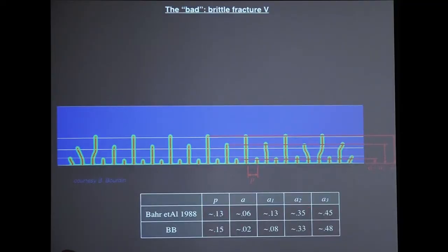If you look at the heights, the distance between the cracks and so on, between the experiment and the computations, there's very, very good agreement. Who knows why? Okay? But there is very, very good agreement. I could argue why, but it would be a different talk. So for some reason, this alternate minimization technique seems to capture exactly what you want, with a caveat about initiation in some setting.